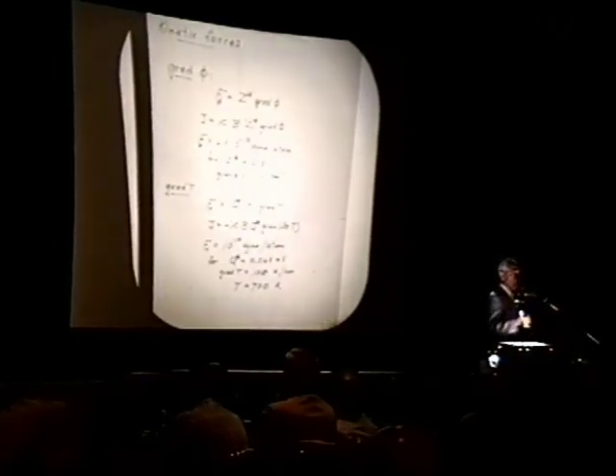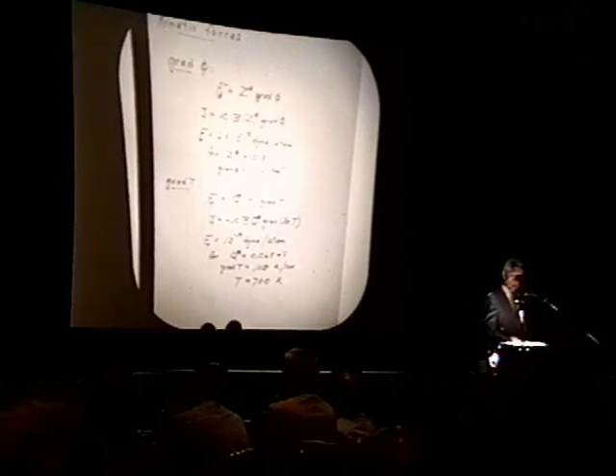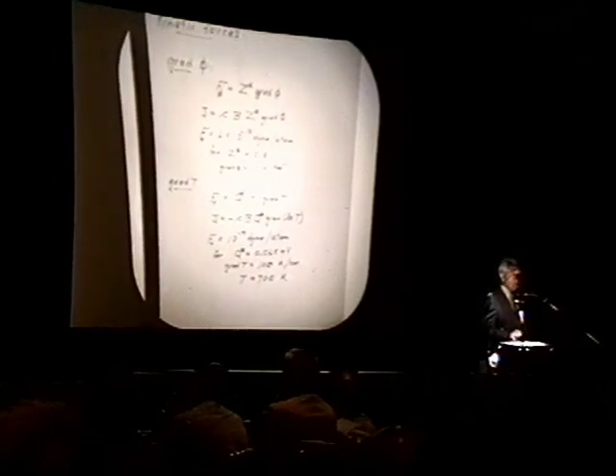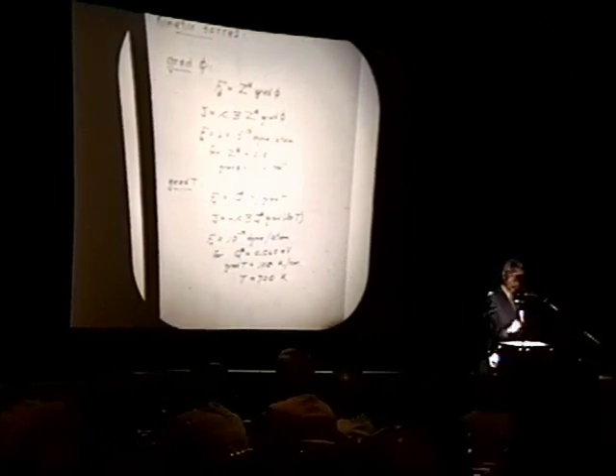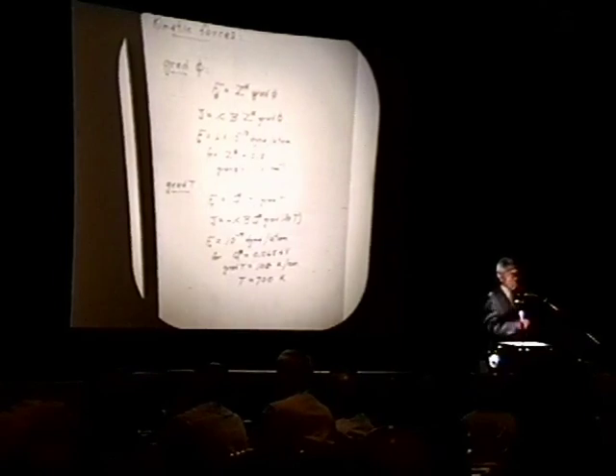The species that's dissolved in there is a tightly screened proton, in the case of hydrogen in a metal, screened by free electrons. And by the way, introduction of the hydrogen into a metal also modifies the energy bands of the metal, so we have not only local but also extensive long-range interactions. But what I can say is that when you establish the magnitude of the Z star, you find that hydrogen in palladium has a positive value, something like 0.6.